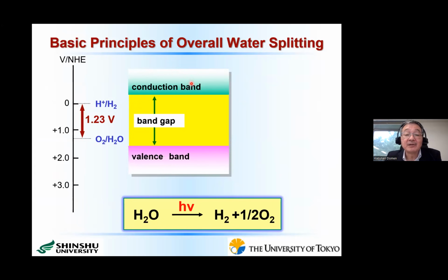This is the band gap position of a particulate photocatalyst, referring to this axis. Under photoirradiation, electrons in the valence band are excited to the conduction band. Then, if the conduction band minimum is located more negative than the hydrogen evolution potential, these photoexcited electrons are thermodynamically able to split water to produce hydrogen.